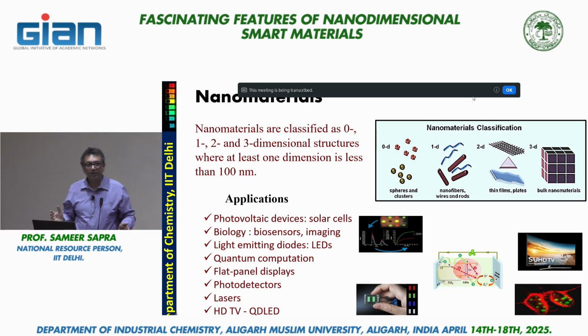And this happens typically at sizes which are below 6-7 nanometers for most semiconductors. As I said, for lead sulfide and a few others, gallium arsenide maybe, it's about 20 nanometers at the most. So if I go to about 50 nanometers of lead sulfide particle, it doesn't make any sense to call it a nanoparticle, right? Because it's not going to do anything for me which is different than the bulk material.